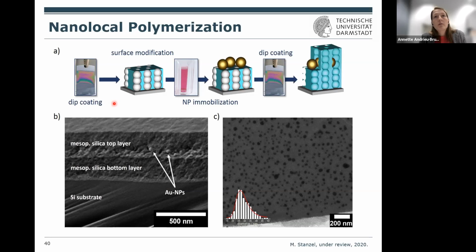The initial work on this was demonstrated on nanoparticles from the group of Zouheir in Mulhouse in France. And they always used these nanoparticles and monitored with AFM the slight changes at the surface of the nanoparticles. And they could even show that the polymer amount reflects the plasmon field distribution.